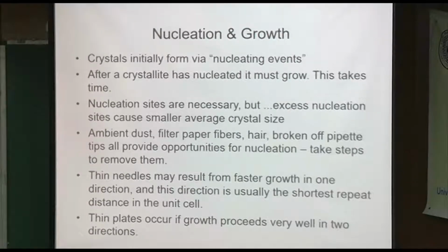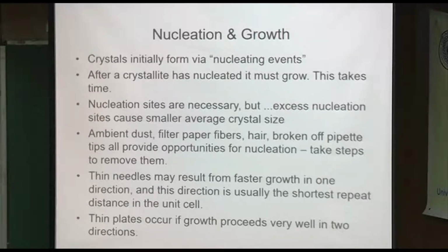If you consider what's happening when crystals grow, the shortest dimension of the unit cell is usually the direction where a needle will grow. Why? Because it's the fastest face of the growing crystal. And so the nucleation to further grow takes place there. So if you're looking at some kind of interesting conductive material where you want to see where the conductivity axis is, it's often the needle axis because things stack up that way easily. And plates, correspondingly, they grow in 2 directions fast, but not in the 3rd direction.